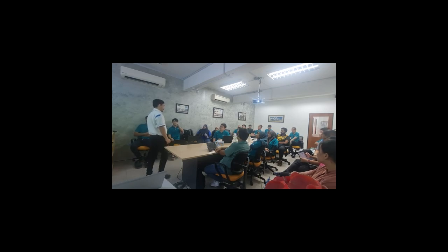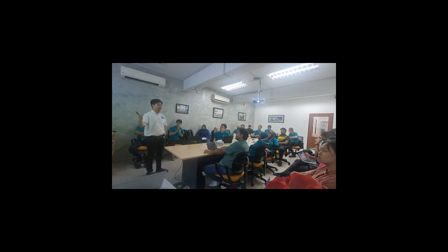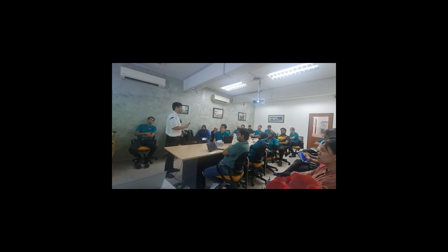Percentage over the cement content. Yes, correct. Generally we measure admixtures versus cement content. Total cementitious content. The binder or the cement? Total, but the binder is part of the cement. Total cementitious, whether it's SCM or not. So it's generally measured by cement. The range can be from 0.2 to more than 2%.